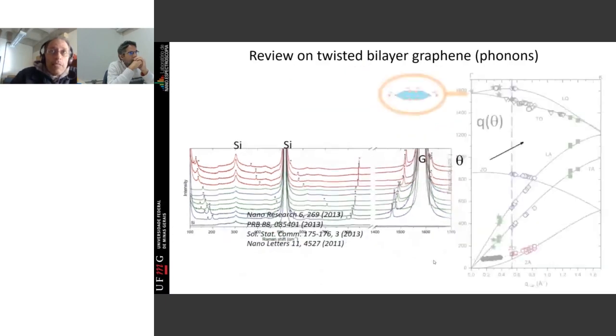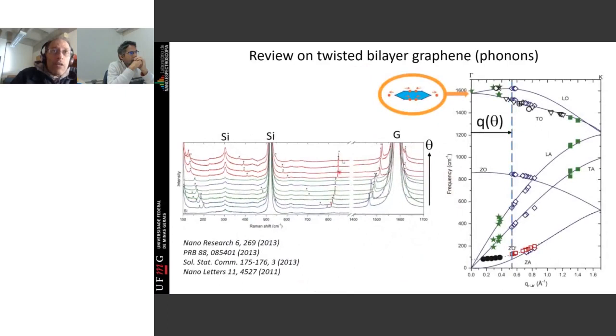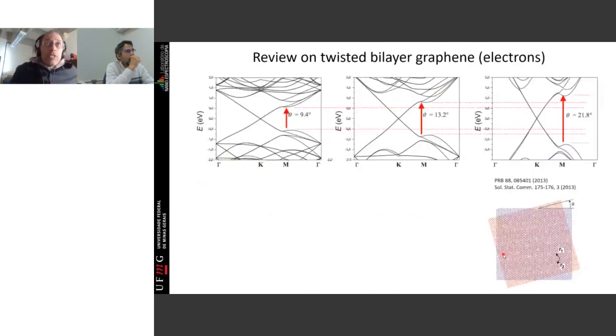And what happens is that when you change the angle here, the twist angle, you are changing the size of this vector of periodicity, and you are spanning the so-called Brillouin zone of the material, and these are the phonon structures. So what you see here is the entire phonon structure, the entire vibrational mode structure of the material by just twisting one layer with respect to the other, okay? Now let's look into the electronic structure. These are the electronic band structures. These are the electron bands.